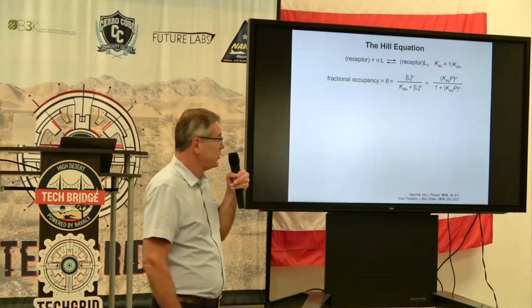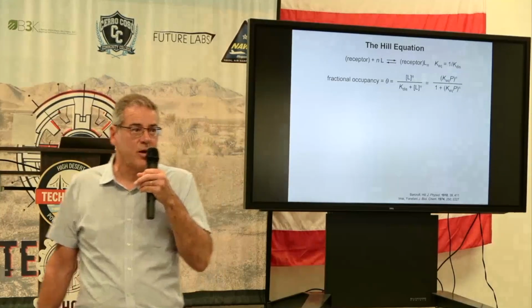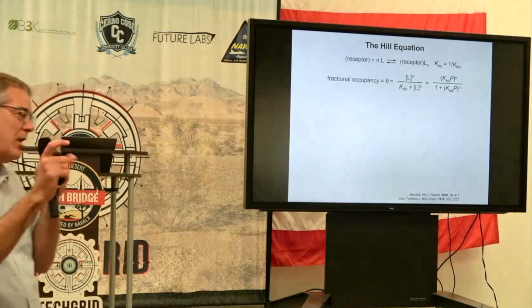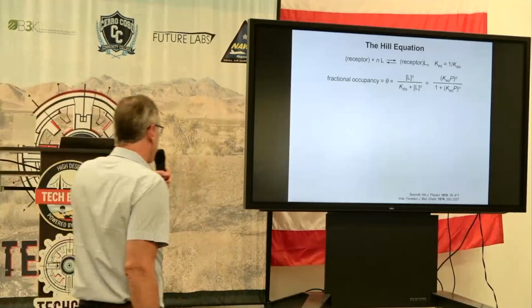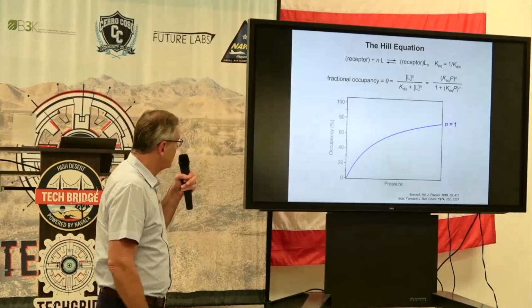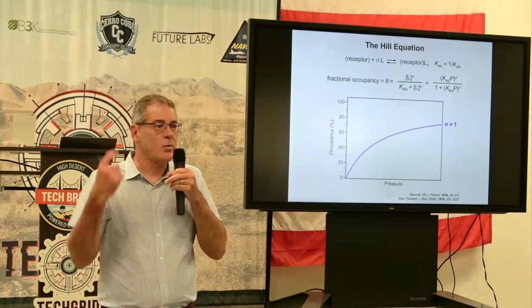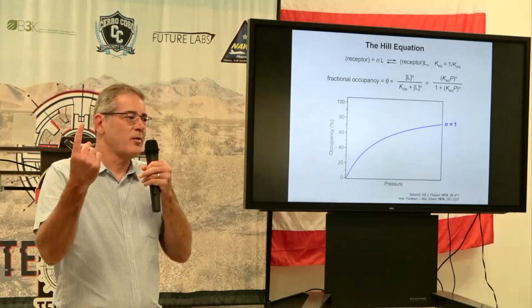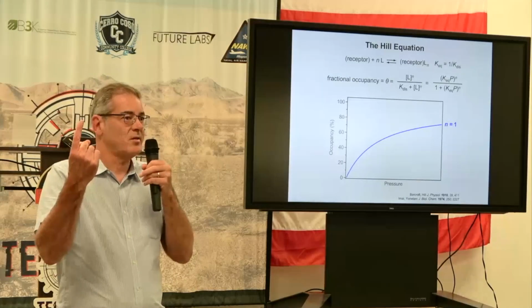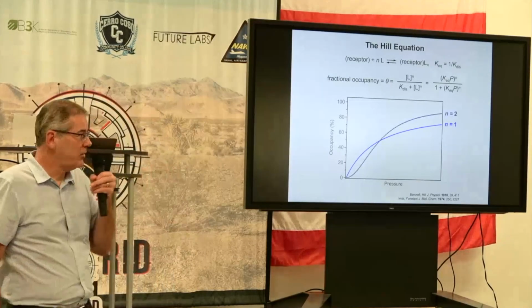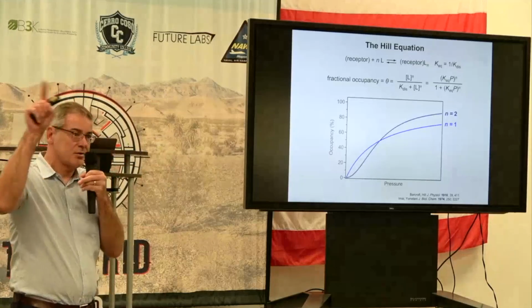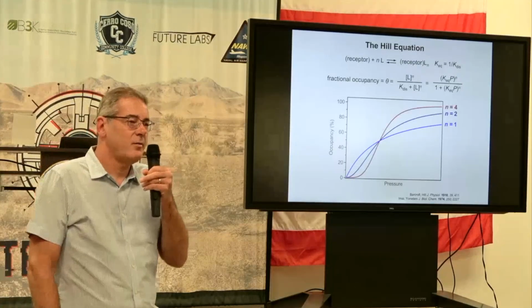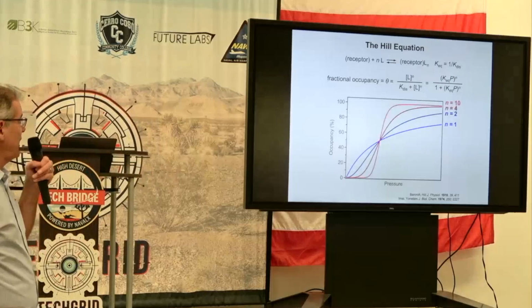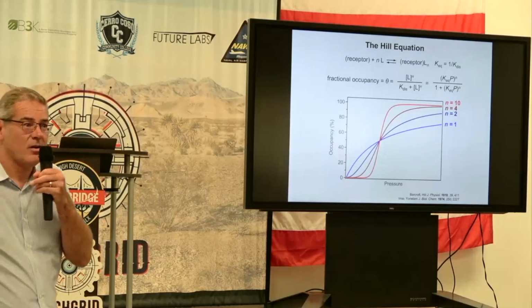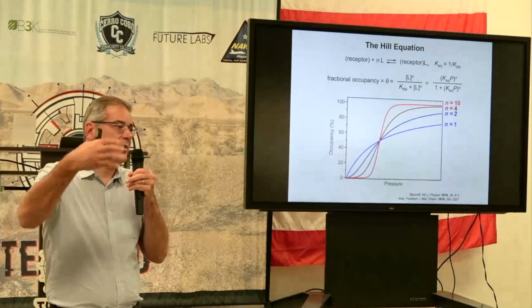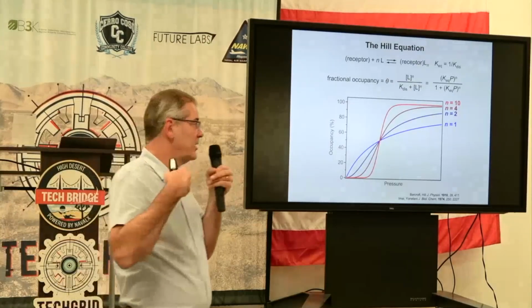And we're going to be dealing with pressures, so here's the same Hill equation in terms of pressures. Again, n is the exponent. How many molecules does it take to drive the reaction? And so let's look at some values of n. If n equals 1, this is non-cooperative behavior, and you get a Langmuir isotherm. If we increase n to 2, you see a very shallow step starting to emerge. At 4, it's a little sharper. At 10, it's much more prominent. So we'd like to design systems where n is very large, and we have specific cooperative binding.